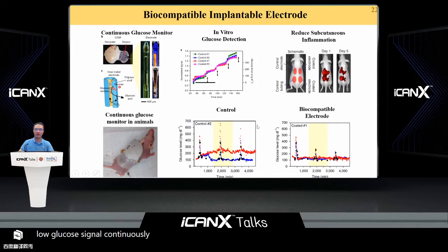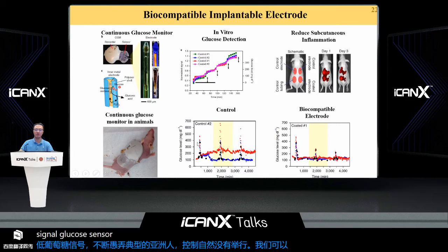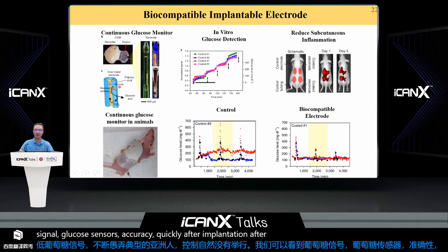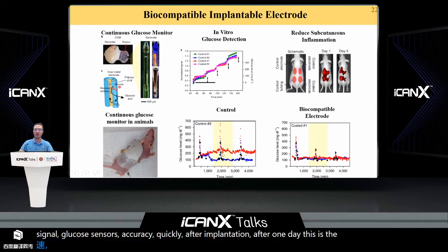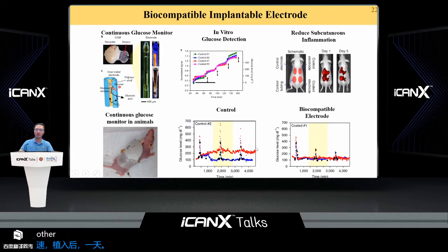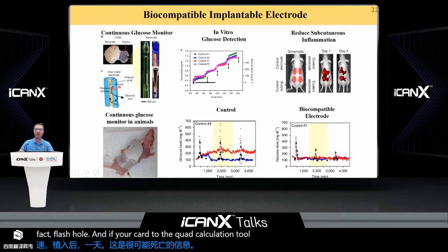Here are two typical results for demonstration. So here is the control electrode without coating. We can see that the glucose sensor shows inaccuracy quickly after the implantation, after one day. This is very likely due to the inflammation of the implanted electrode, and it required calibration to correct the signal every day.